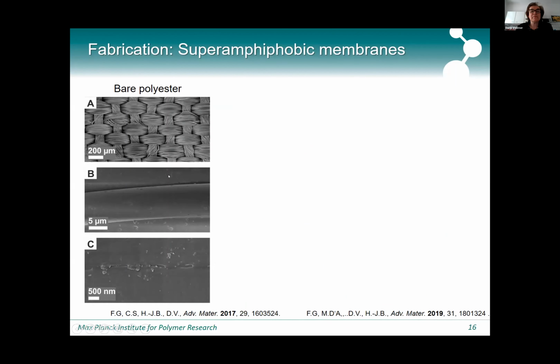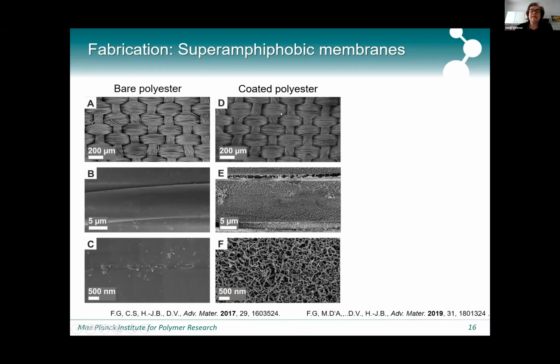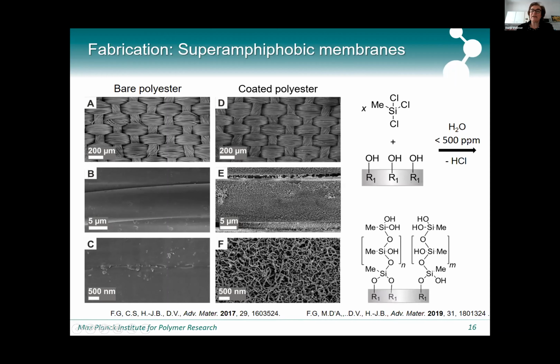We went for commercial polyester membranes. Here you see them at different magnification. They are composed of fibers. And then after treating, at low magnification, the membrane appears unaltered. However, if you go to higher magnification, then you see that they are now coated with these kinds of nanofilaments. How did we do it? We placed our textile membrane into a solution containing trichloromethylsilane in toluene in the presence of a tiny amount of water. Then we have a hydrolysis and condensation reaction, and the filaments grow on the textile.